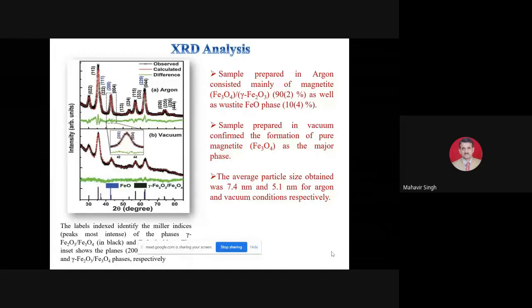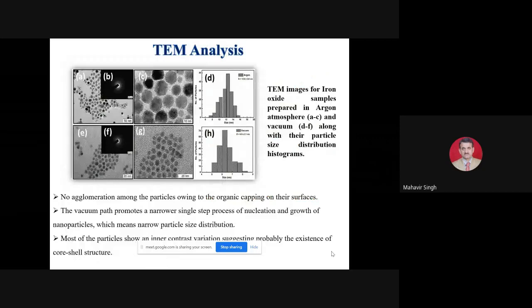Having a spinel structure, so clear evidence. So this is exactly the shape. There is no agglomeration, because dear friends, if you want to use it in the health sector, your shape, your size and your morphology should be clear. There should not be any kind of agglomeration. They should be stable in aqueous medium and without any agglomeration.